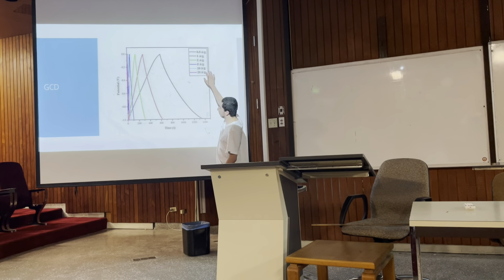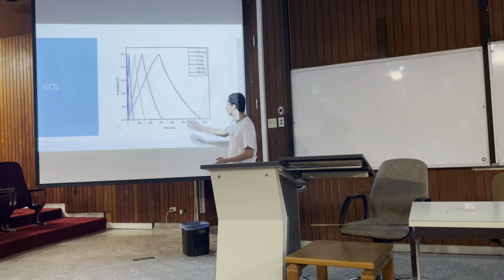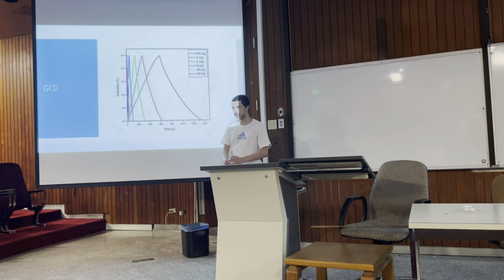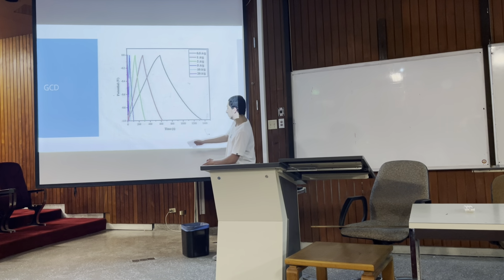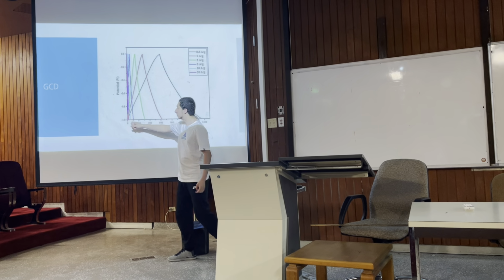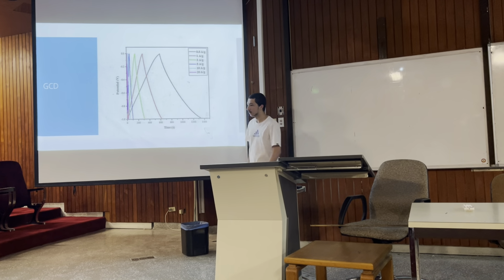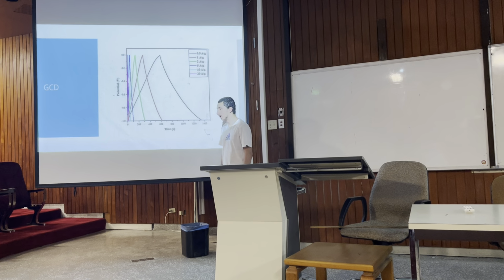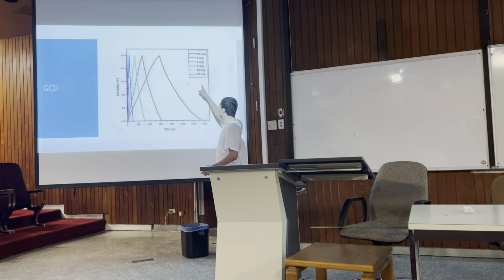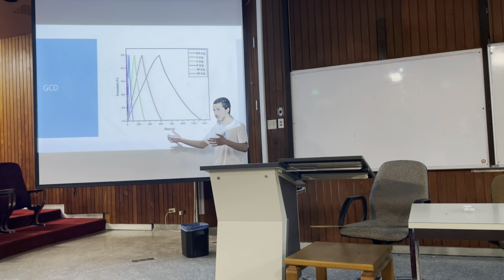This depends on the current output that you design. But we see here it's almost close to 0 seconds if you want, for example, 20 amperes. Also, this is per gram. In a realistic case, if you want to build a car where as soon as you step on the pedal you get this acceleration, you would build a relatively large supercapacitor.